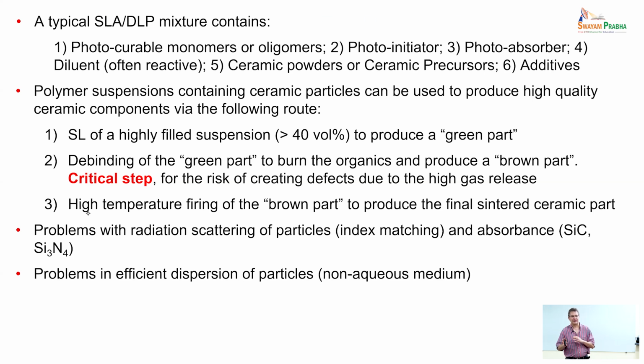The other approach, photopolymer volumetric additive manufacturing, has the advantage that it is not a layer-by-layer technology. It's much faster. It gives you very smooth surfaces. But in this case, it works very well with certain polymers. But for ceramic systems, you have the problem that the light has to go through not just the thickness of the layer, like in the case of DLP or SLA, where the thickness of the layer is typically from 25 to 100 microns.